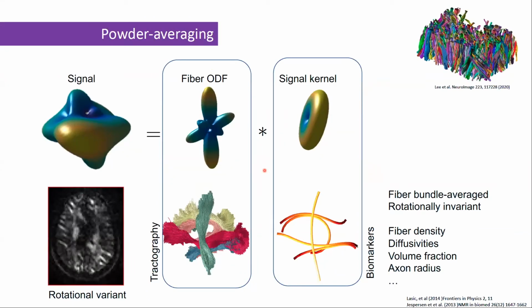One concept that I have to highlight a little bit more before we can move to the actual model of axon diameter mapping: our diffusion weighted signal is a convolution between the fiber orientation distribution function and a signal kernel. The fiber ODF is typically used for tractography because it shows basically the main directions of diffusion, and we can integrate along those directions to reconstruct our streamlines. The signal kernel is basically a fiber bundle average signal response, which is rotationally invariant. And we can use that particular kernel to obtain all kinds of biomarkers: fiber density, diffusivities, volume fractions, axon radius, and so on.